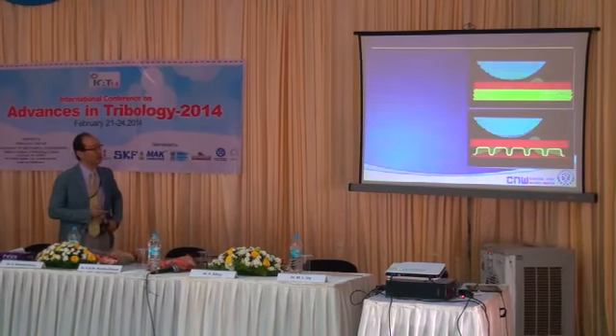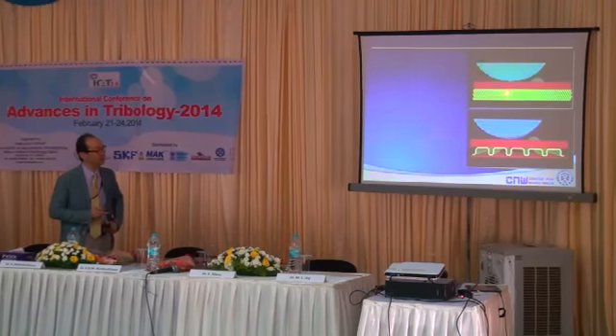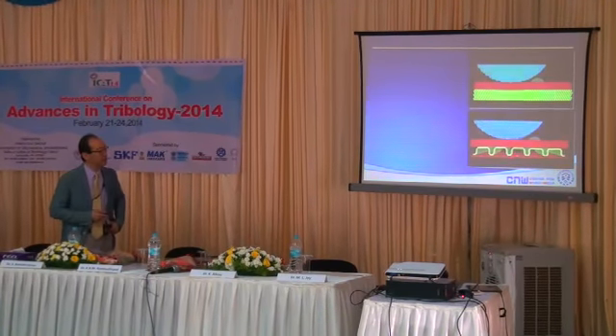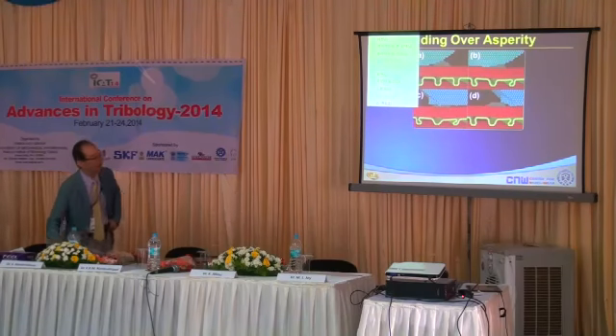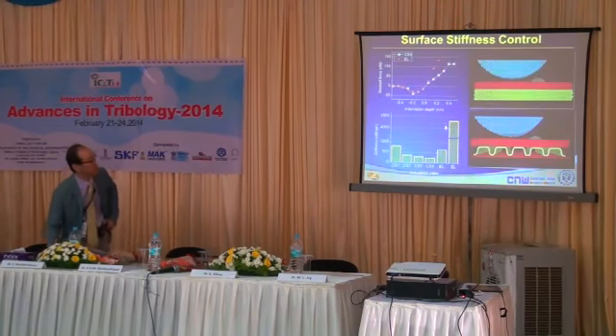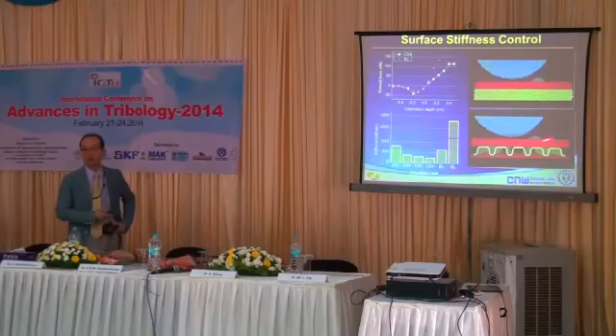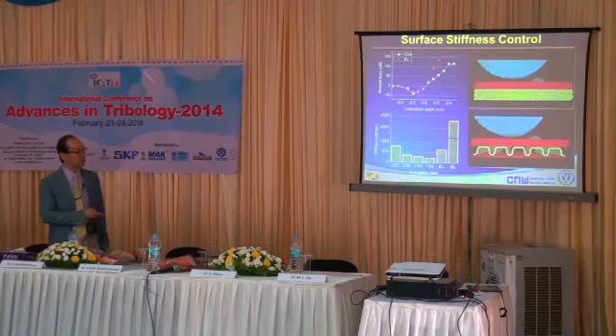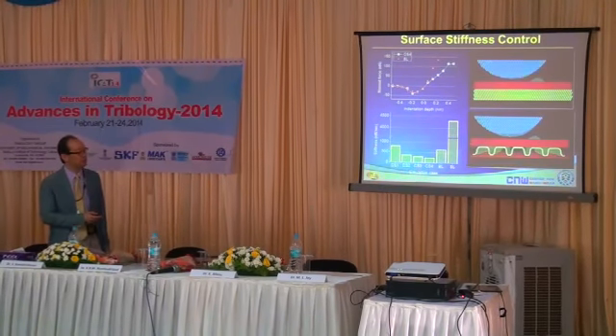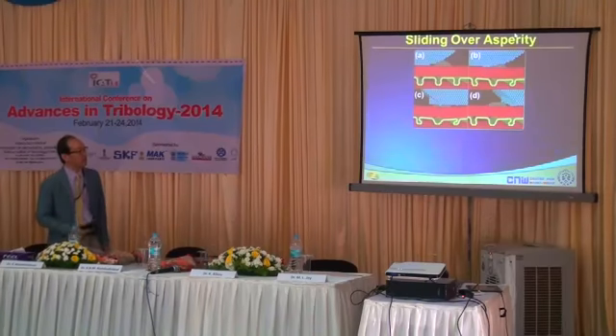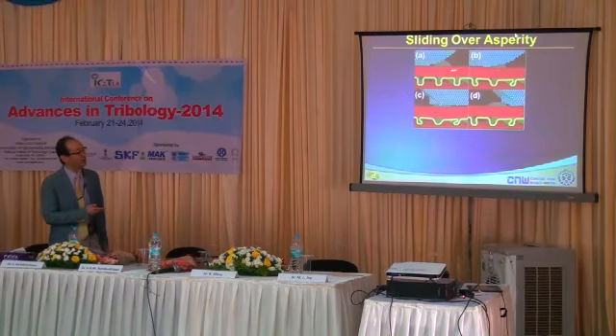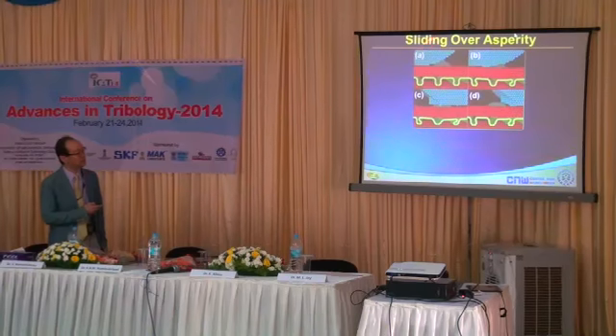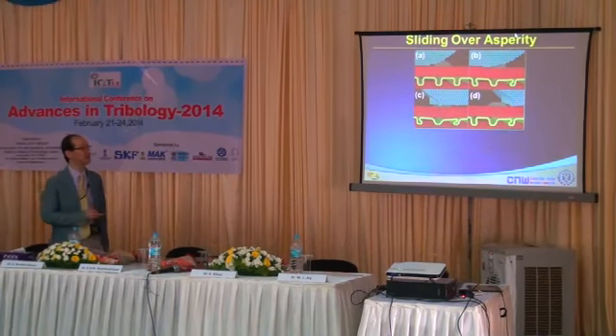What you're looking at here now is contacting of the tip against the bilayer surface and against the corrugated surface. But what we're looking at is the stiffness of the bilayer is much stiffer, as expected, than the corrugated surface. And we measure the stiffness by performing the simulation for all our designs, and we're able to quantify the stiffness for different designs. And when we slide over the asperity, what you're looking at here is the asperity that I showed before. It's the tip in contact with the surface, and now it's sliding in the tangential direction.